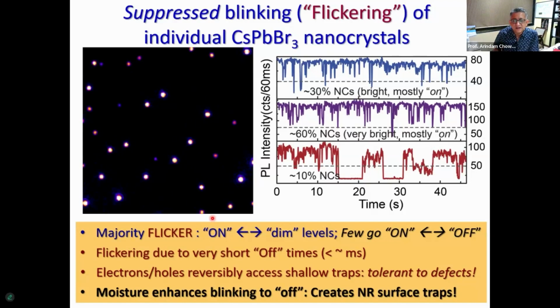Essentially, this tells you that it's indeed blinking, but the blinking timescales are very fast. The turn-off timescales, which are represented by these short durations of off times here, are typically sub-milliseconds or so. And this is, again, one of the very, very interesting aspects of these perovskites.